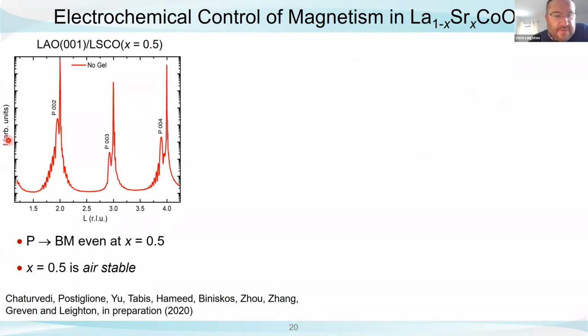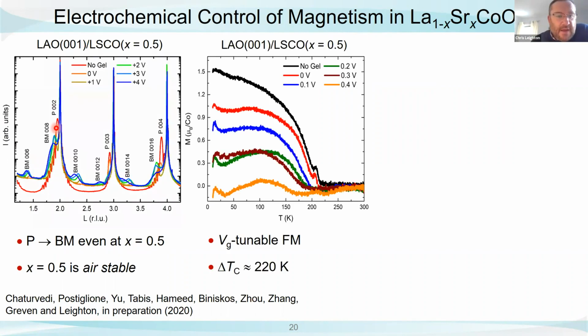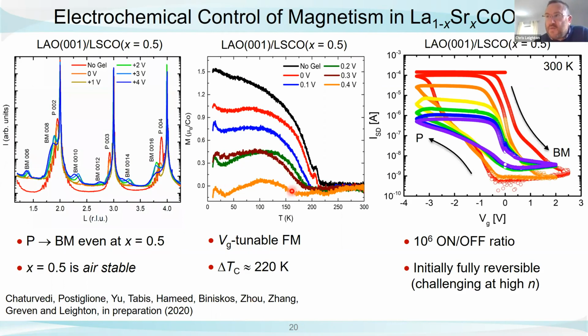So we can start with a perovskite film. We can put on an ion gel. We can apply voltages. We can completely eliminate the perovskite phase, turn on a Brownmillerite phase. As we do that, we can controllably decrease the magnetization as it goes towards the antiferromagnetic insulator. We can kill the material's Curie temperature. And then I think most interesting, when we measure the source-drain current in a transistor, we start in a perovskite phase where it's a high current, it's a highly conductive material. We can drive it to the Brownmillerite with a 10^6 on-off ratio.